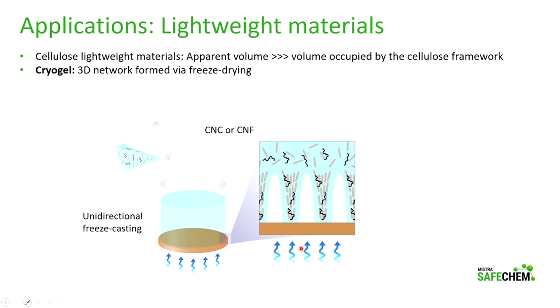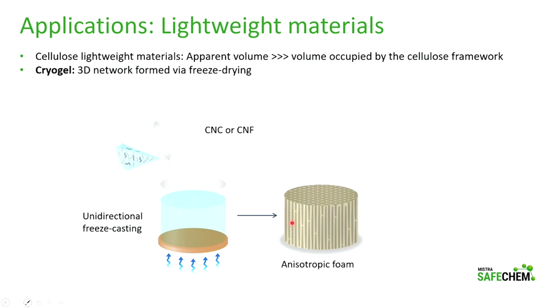So we take dispersions of either the CNCs or the CNFs that I showed before. We do something called unidirectional freeze casting. The idea is that we will use ice as a template in order to make these materials grow in a specific location. And then here I just show a little more into detail. So when the ice is growing, this will help us to get some walls. They will help us to make a template of our materials. And then we end up with an anisotropic material.